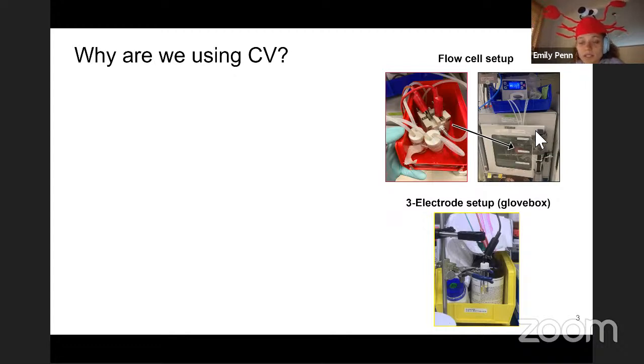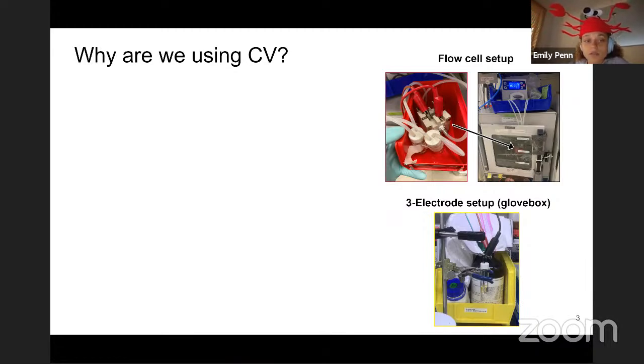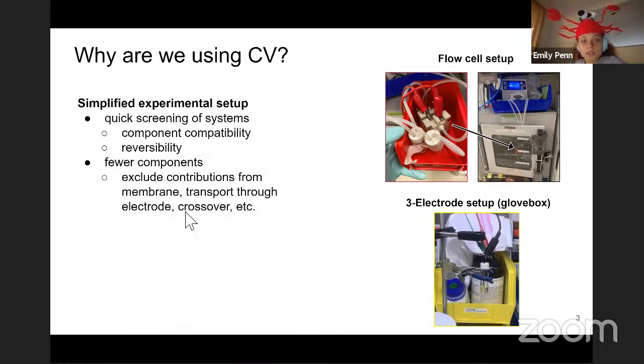We sometimes place this in an oven. So you might have seen this kind of weird looking setup in the 184 old vacuum oven, where we've been working on some low temperature cycling experiments. And with this setup, we can test our quinone mixtures in a flow battery configuration. But we also do experiments in the glove box with a 3 electrode setup. So that's where we do CV, and this has some advantages over the flow cell setup.